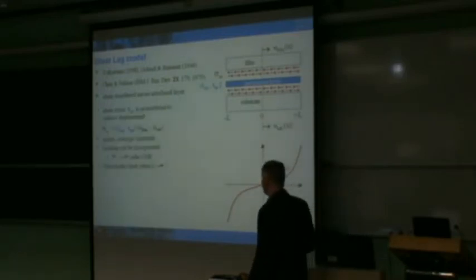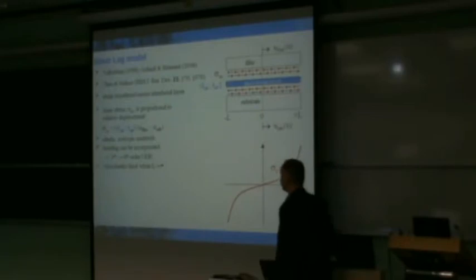And so pictorially, what you'll expect to see is that the shear strain is zero at the center of these structures, and then as you approach either edge, plus or minus L in the x direction, you maximize the shear strain that's there, or the shear stress in that case. And the shear stress is assumed to be proportional to the slip between the displacement in the film and that of the substrate, and this proportionality constant here is really the ratio then of the shear modulus to that of the thickness.